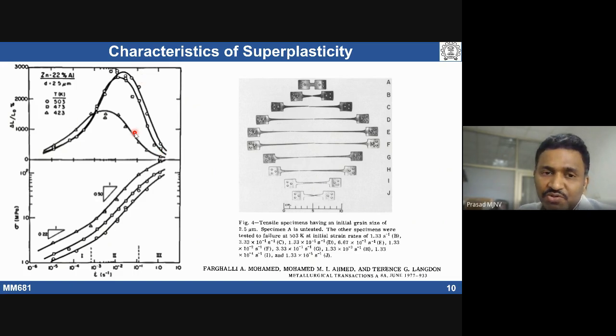The purpose of showing this slide is basically, at a fixed grain size, if you deform material at three different temperatures, what is the effect of temperature on the shape of the superplastic curves, the sigma versus strain rate and ductility versus strain rate curves. So with increasing temperature,